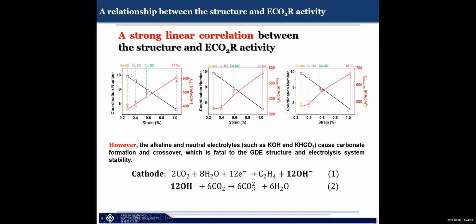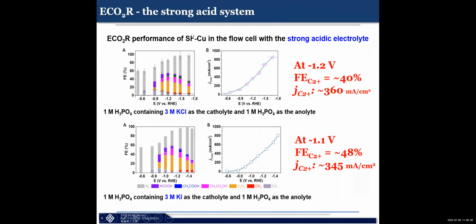Okay, so now typically people have to use KOH, or for neutral electrolyte, KHCO3, but they will eventually lead to formation of carbonate and crossover. So eventually the stability of the device will not be that great. So we performed one experiment proposed by the Sargent group, Edward Sargent from the University of Toronto. So they actually use a strong acidic electrolyte. So we actually repeated that in similar conditions.